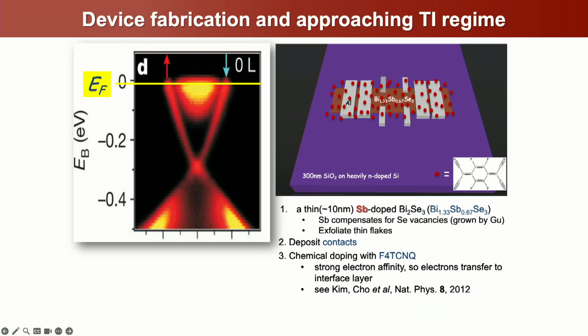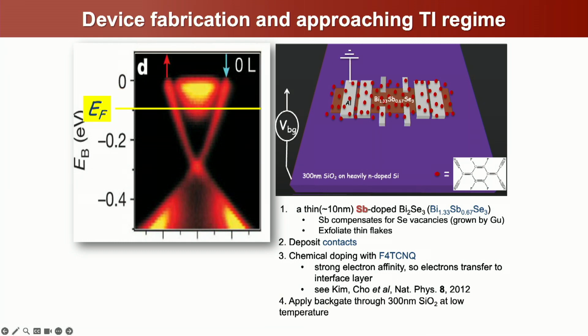And then on top of that, we finally use an electrostatic gate, a back gate or a top gate, to be able to tune the Fermi energy all the way through the Dirac point in these systems. And so this allows us to not just access the topological region, but tune all the way through the topological region to distinguish between topological and non-topological behavior in transport in these sorts of materials.